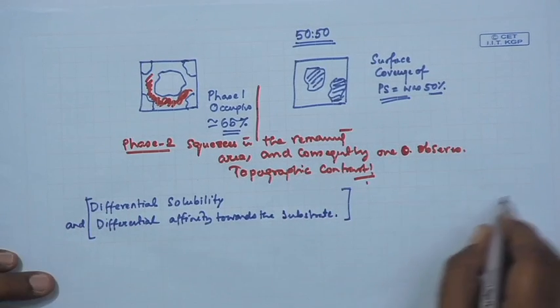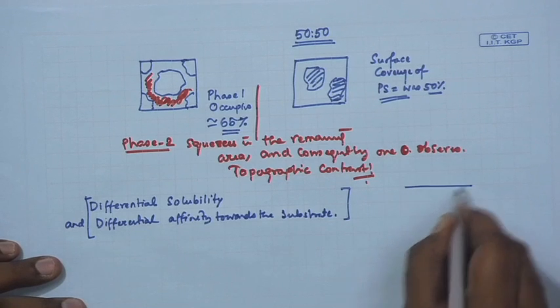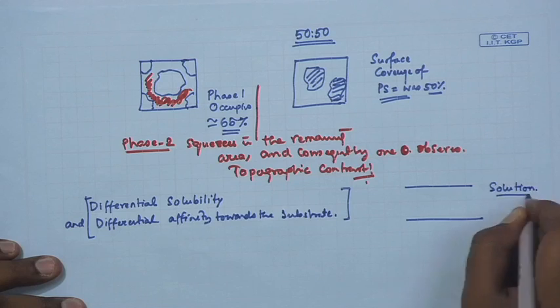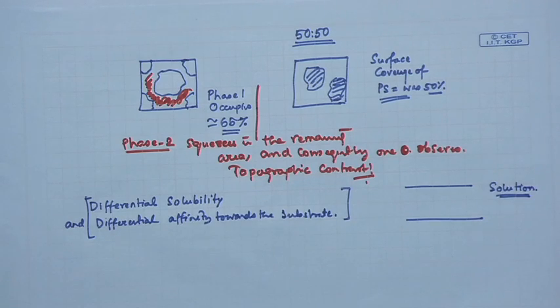So, now it is easy for you to understand that in the same solution, you in fact know that the intrinsic concentration has to attain the saturation concentration, then only the deposition will start. And therefore, it is obvious that the polymer phase which has lower solubility will in fact start to phase segregate ahead of the other polymer, and therefore, that deposits when the substrate is flat.